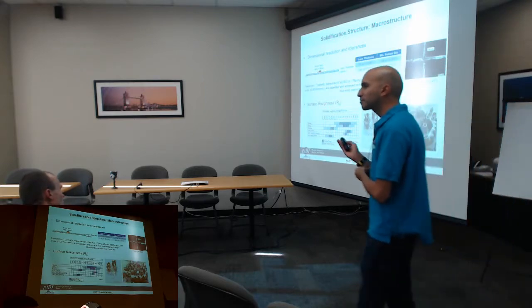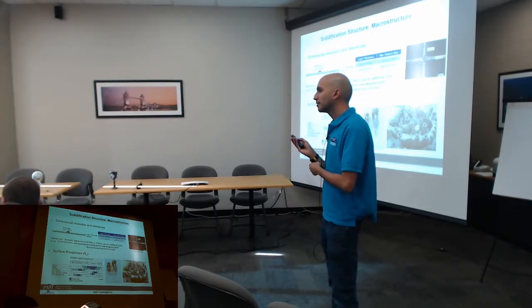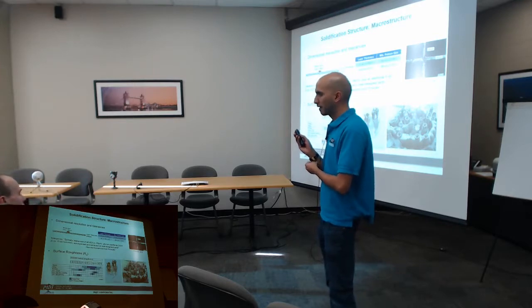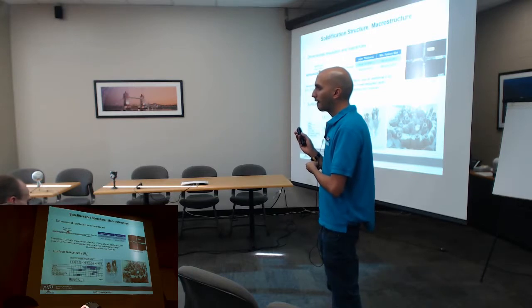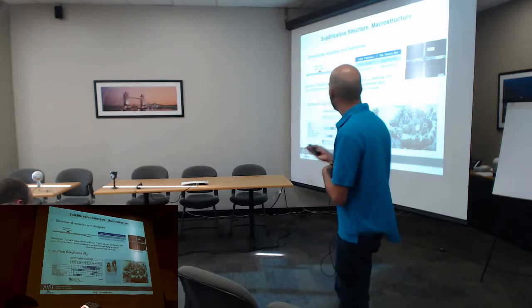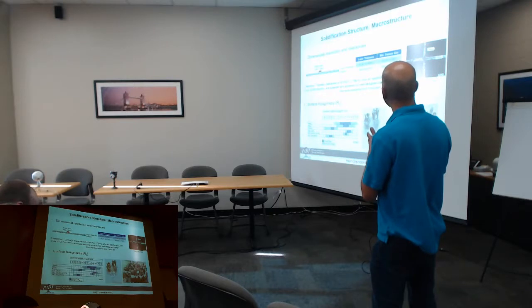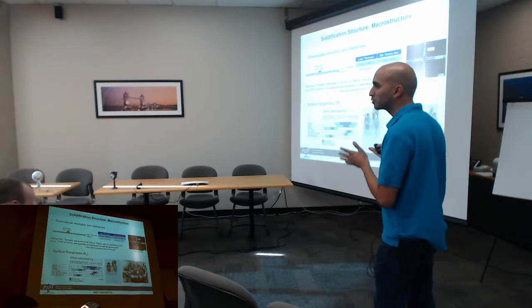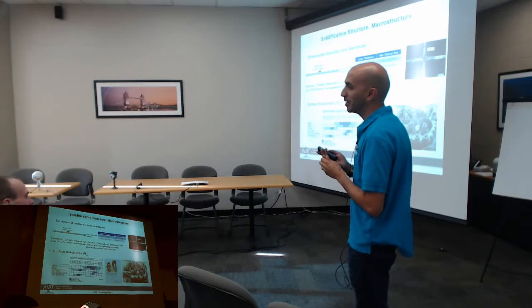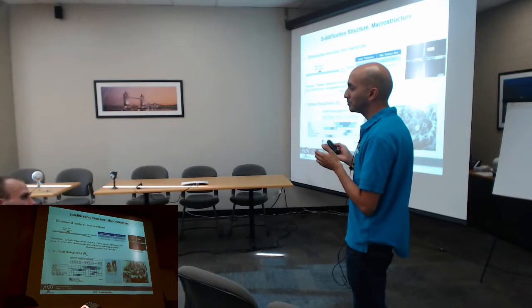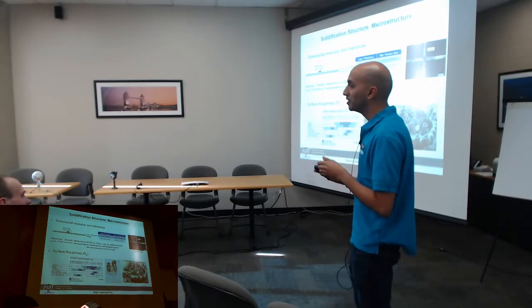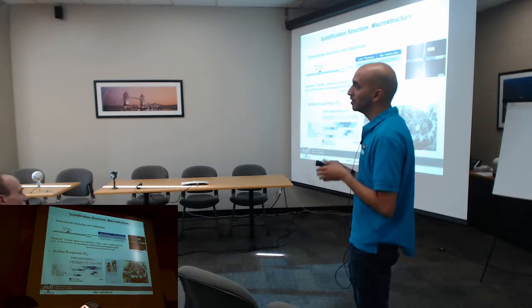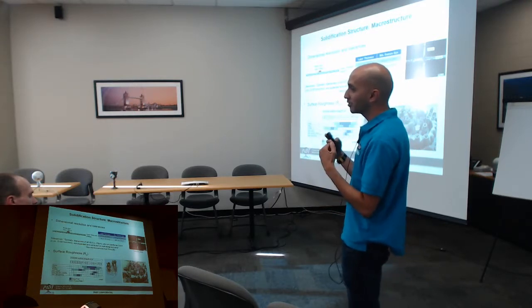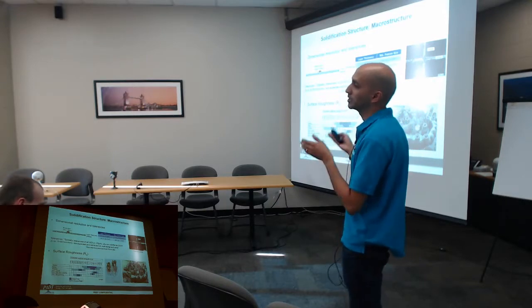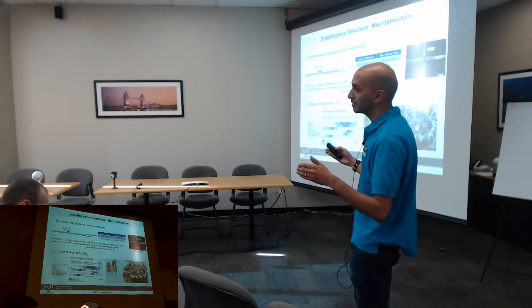Yes? So you have feature minimum is 6 thousandths, plus or minus 3. What about a wall thickness? I wouldn't imagine that you could have a 6 thousandths wall. The minimum that you can make, and this is from a paper, is people have shown 250 microns is the minimum you can make for walls that are not very tall. Proto Labs likes to quote a 1:40 ratio in their aspect ratios of how tall you make a wall. So if you keep that calculation in mind, then you can achieve 250 microns at a minimum, and then that will scale as your wall gets taller.